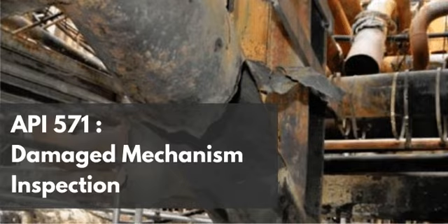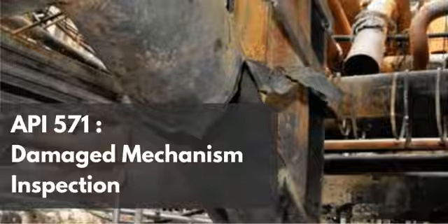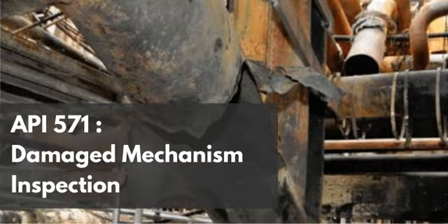Exactly right. Okay, so we've defined the precise nature of the failure and the microscopic weapon used. Now we really need to address the susceptibility of the materials. Material selection is everything here. Section 3.3 identifies the primary material at risk. It's carbon steel, but it makes a very specific metallurgical distinction. It explicitly calls out carbon steel that is non-PWHTD. Right, meaning it has not undergone post-weld heat treatment. That is the definitive material parameter for this mechanism.